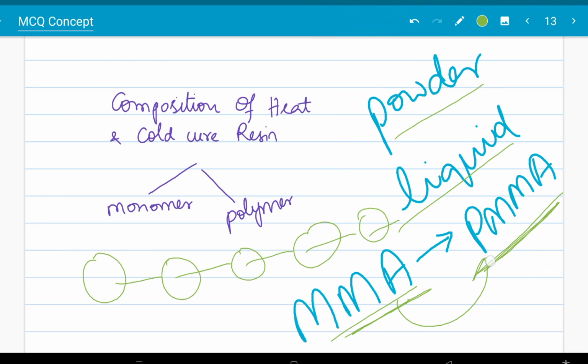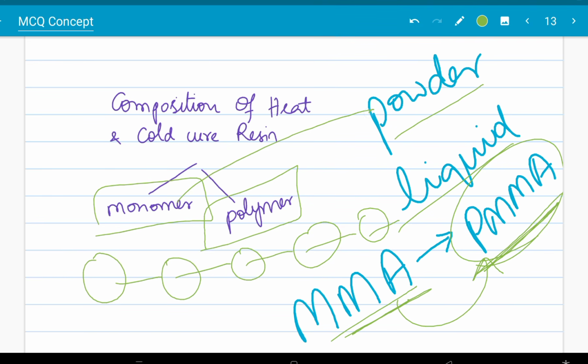When you mix monomer and polymer, we are going to achieve polymerization of methyl methacrylate. When pure methyl methacrylate is used in polymerization, you get polymerization shrinkage to a real extent, which will cause discrepancy in your denture fabrication. So to avoid that and to reduce the heat and other side effects and byproducts, we are using already pre-polymerized, pre-made polymethyl methacrylate to some extent to reduce polymerization shrinkage and the exothermic reaction. So remember there are two components, monomer and polymer. Monomer is mainly the liquid component and polymer is mainly the powder component.